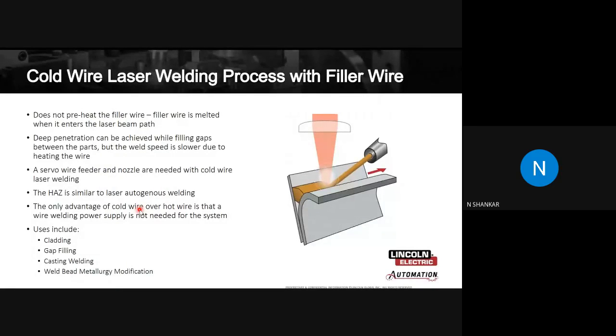Similar to a hot wire laser, in cold wire laser the wire doesn't come preheated, so there will be much lesser heat here. The filler just enters into this and gets melted with the energy that's available from the laser source. A deep penetration can be achieved while filling gaps with this process also. A servo-driven wire feeder is separately given to feed the wire into this. The HAZ is similar to laser autogenous welding because it's absolutely a cold wire that's being fed and only the laser energy is coming in. So it will have almost the same heat in HAZ similar to an autogenous welding application.